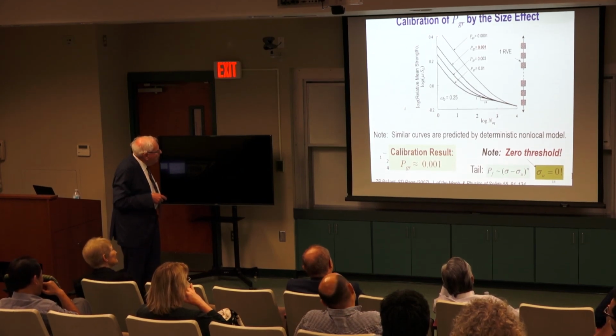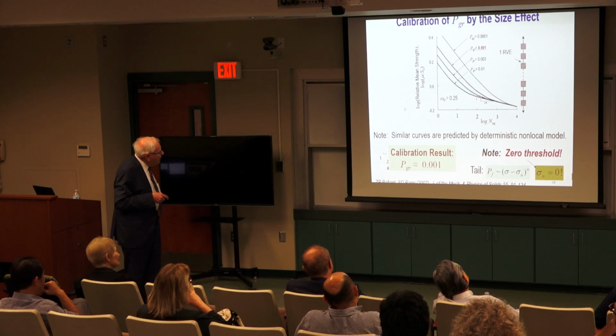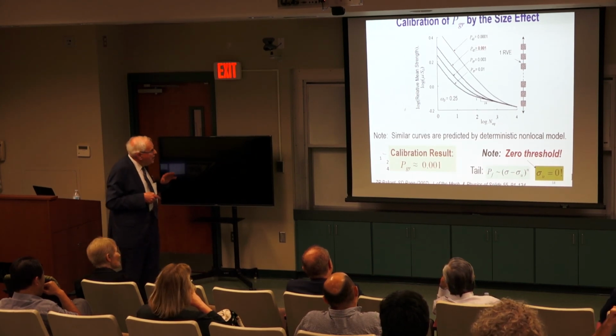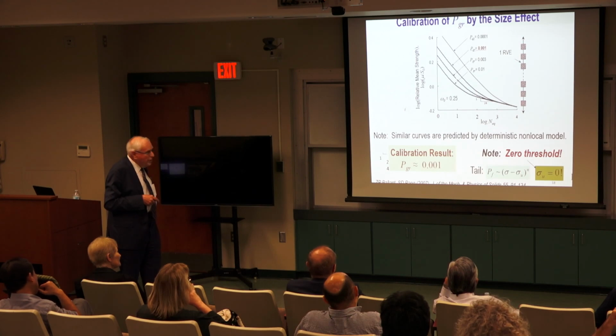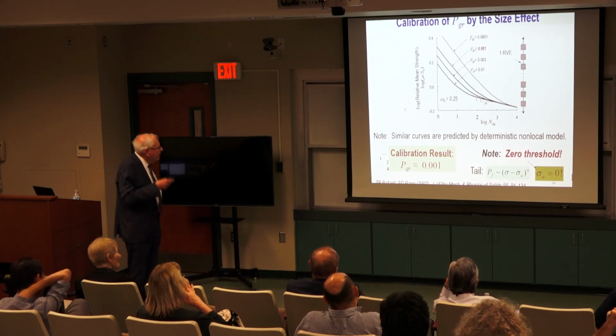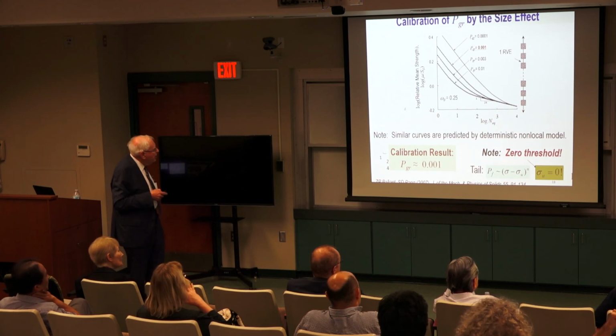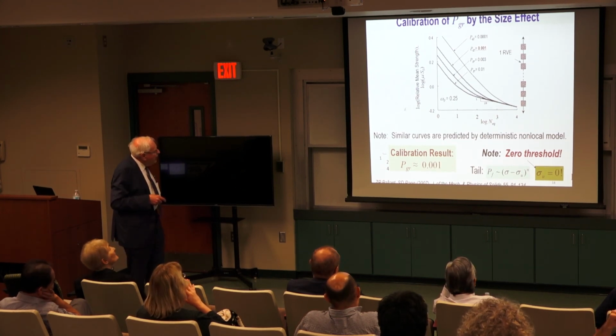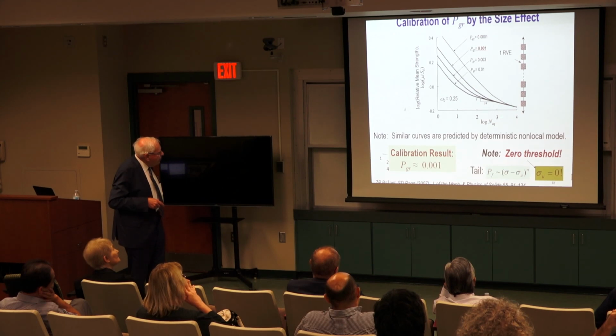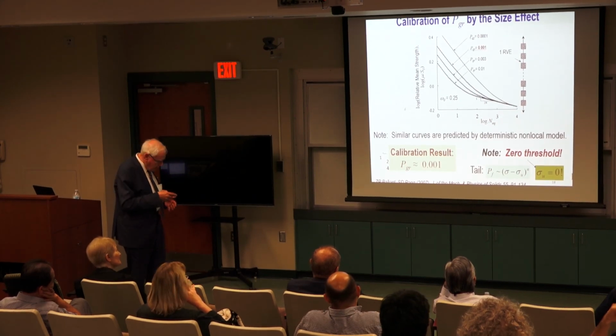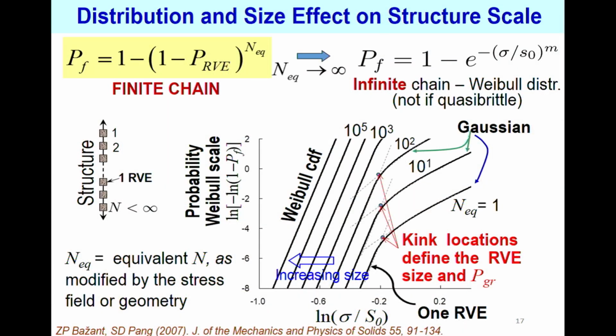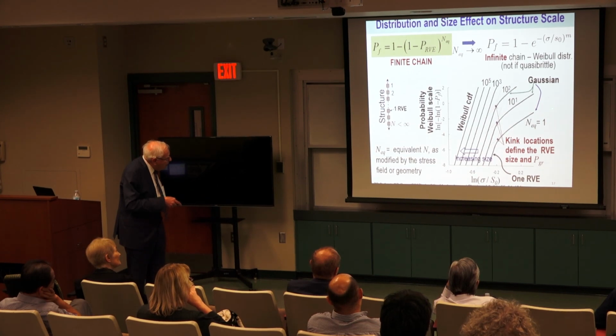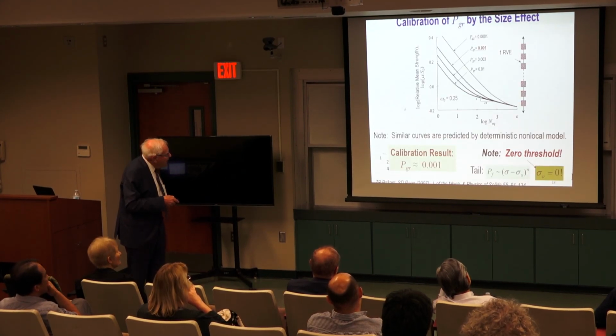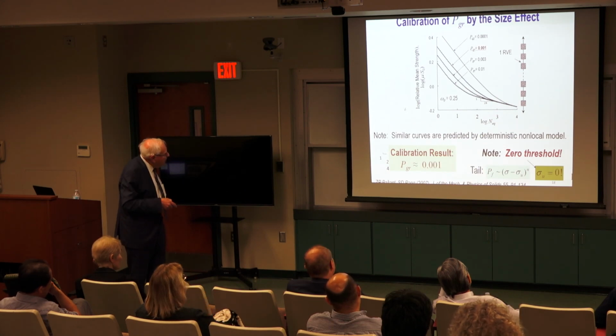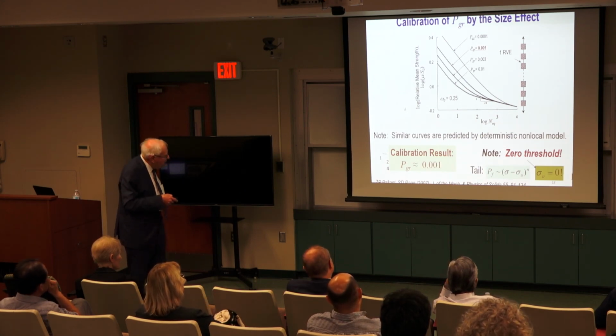And by the way, in size effect, and this is the beauty of it, we need to consider only means. The mean is easy to test. You can test maybe 4 sizes, you need 6 specimens for each size, so it's not very, very large. Now what you see is this. If you change the grading, the point of transition from Weibull to Gaussian, this is the Gaussian Weibull plot, then you find out the size effect is similar but shifts along this line.